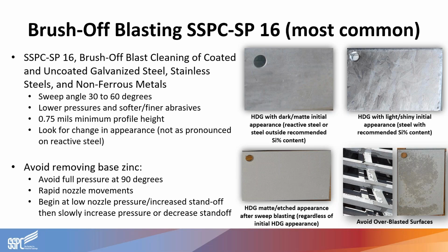This standard requires that abrasive blasting for galvanizing be performed at 30 to 60 degrees and at lower pressures. You'll also use more rapid nozzle movement and use softer and finer abrasives to achieve a minimum 0.75 mil profile height. And then it'll include procedures to assist without damaging the coating in that process. To the right here, there are some images I'm showing you.